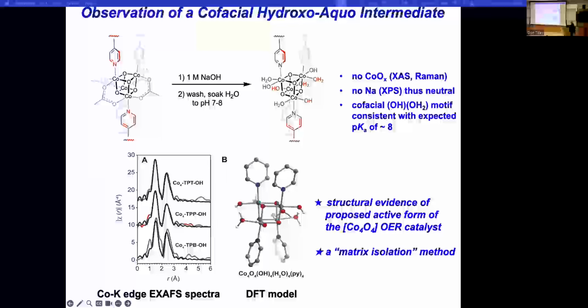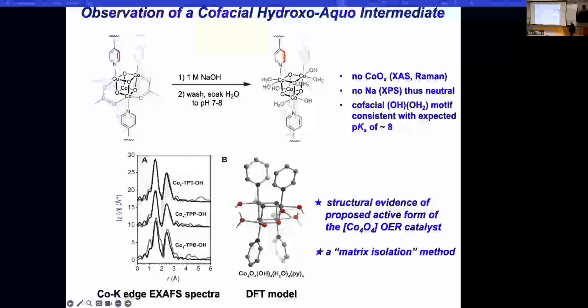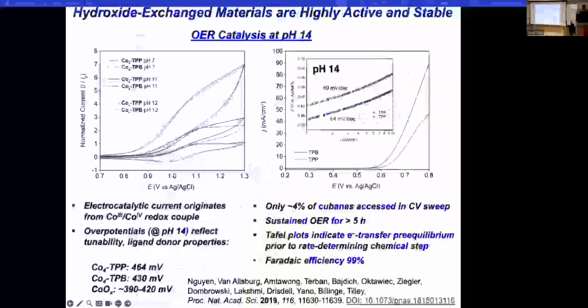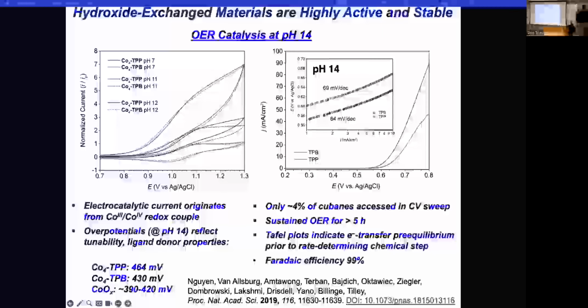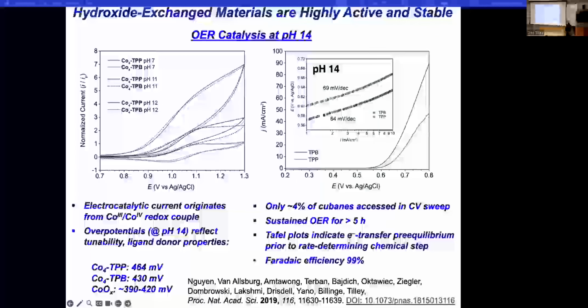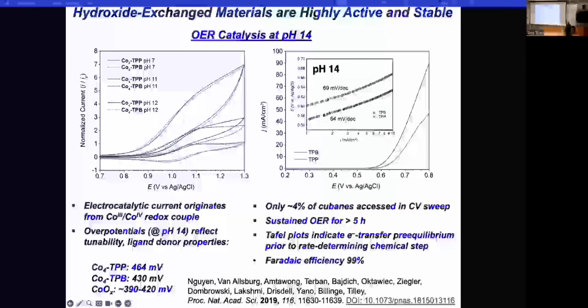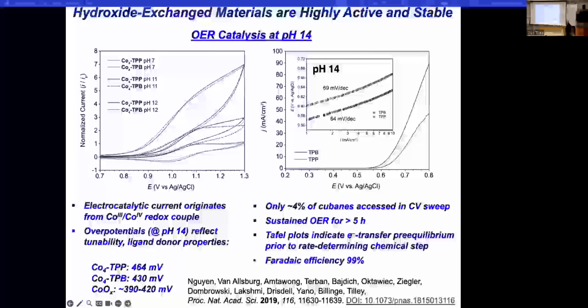X-ray XAFS data by Junko Yano indicated the structure that you see here. So this is a great matrix isolation type of method where we can isolate a cube like this and then do spectroscopy on it as it goes through these reactions. Briefly, electrocatalytically, we see the catalytic wave come in right at the 3-4 couple. That's what we see in solution, right? And then the other behaviors that we observe indicate that only about 4% of the cubes are accessed.